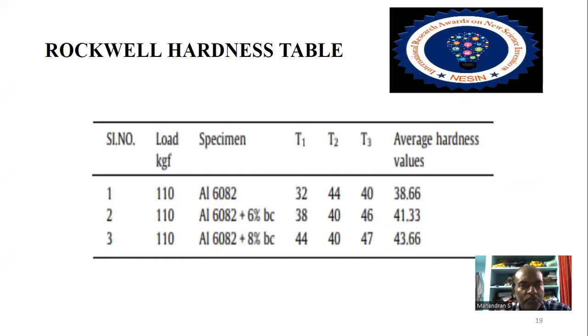This is the Rockwell hardness test table, where a load of 110 kgf is given, and there are three specimens: aluminum 6082, aluminum 6082 plus 6% boron carbide, and aluminum 6082 plus 8% boron carbide. The readings T1, T2, T3 are noted. The average hardness values increase from 38.66 to 43.66. When the percentage of boron carbide added is increased, the average hardness values automatically increase.